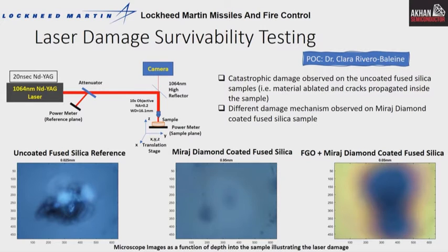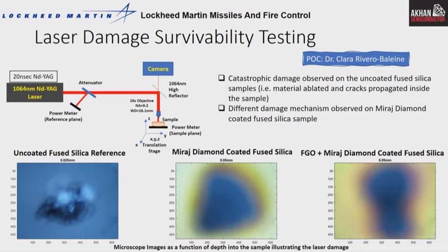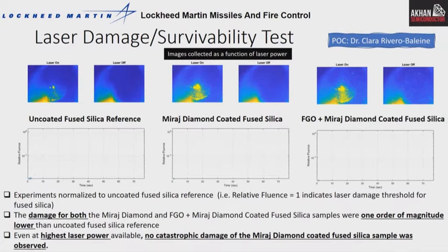In the diamond-coated fused silica and the FGO-protected sample, we see something else. We see that the damage is different in that it doesn't ablate or crack the material. Rather, the energy is absorbed, and we see a crystalline change, where it actually reverts from diamond into graphite. So it still continues to dissipate the heat that's coming through without actually failing. And this test was done, again, normalizing the function of the power to the uncoated fused silica reference sample.